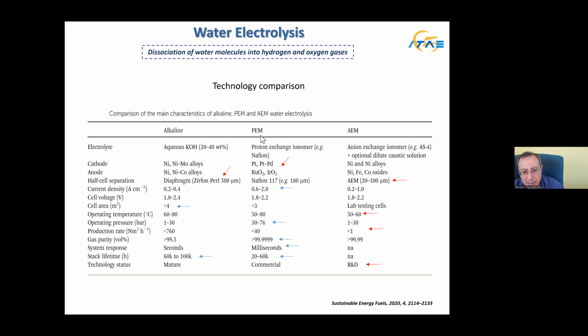In the case of PEM, proton exchange membrane electrolysis, we have precious metals, platinum, ruthenium, iridium. We have perfluorosulfonic membranes that are also expensive. But how to compete with alkaline? We can operate on the current density. Using this technology, we have a low ohmic drop because of the good proton mobility, and we can operate at the high current density, in this case, 2 amperes per square centimeter.